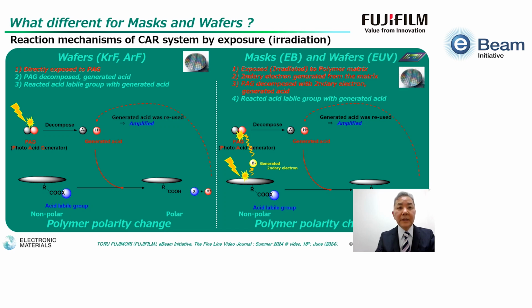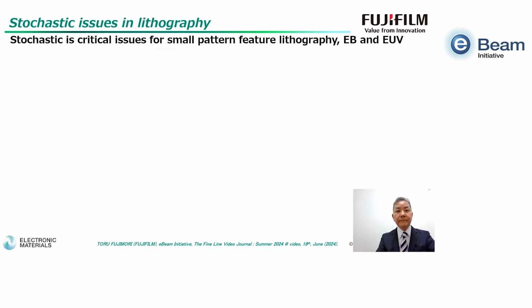Interestingly, in the case of EB lithography, of course on the wafers, the mechanism is the same as EB's. And EUV is a kind of soft X-ray, so it's kind of the same. So considering the resist development, EB and EUV seem the same or similar. Stochastic is the critical issue for small pattern feature lithography, EB and EUV.